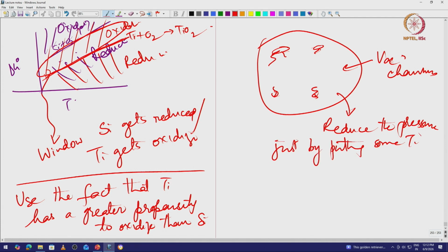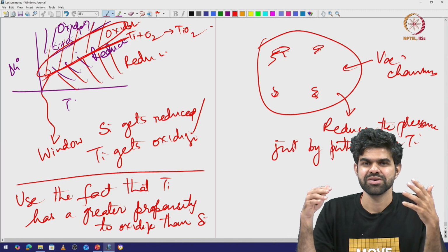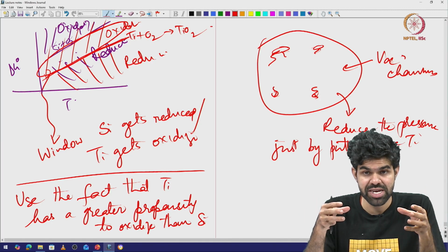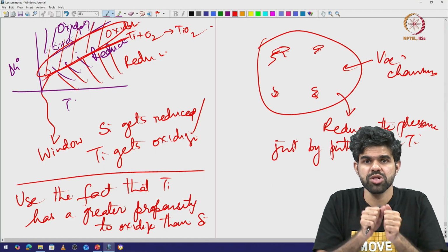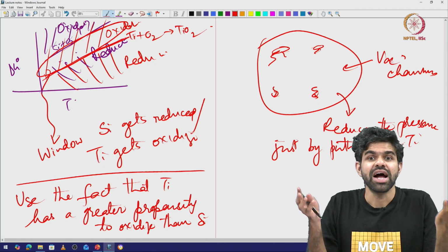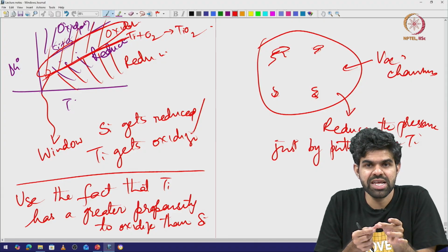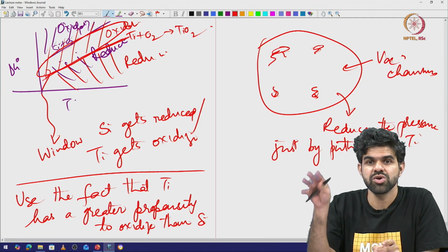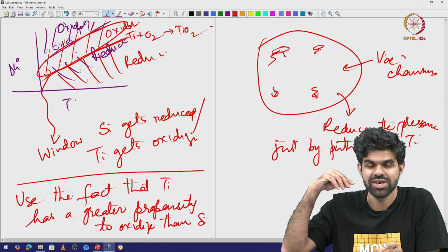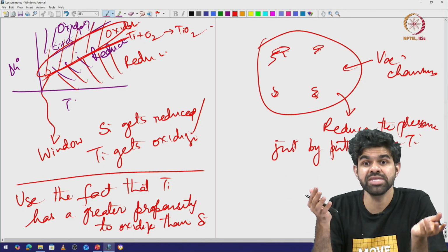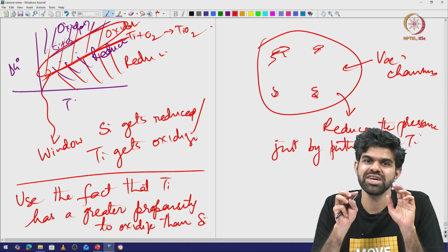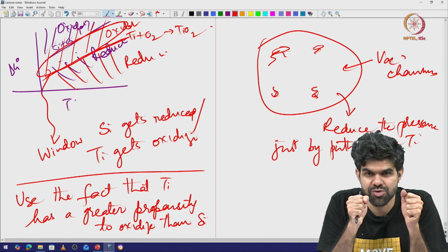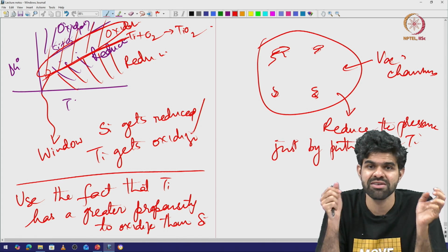This is a ghetto way, I must say, but you can just put some titanium and you will see that the titanium has absorbed all the oxygen or a lot of oxygen, so all your oxygen is in the solid chunk of titanium that you have. So, there is no gaseous oxygen floating around. Titanium has huge propensity to oxidize even at room temperature. So, this delta G naught tells me the driving force for titanium to oxidize even at room temperature, and this is huge. Same thing with aluminum.